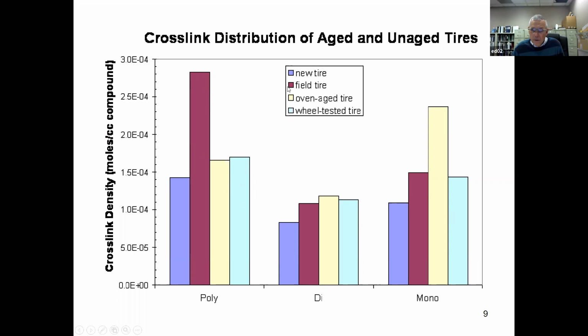So even though the field tire and the oven aged tire have the same crosslink density, all the crosslinks have to show up somewhere in here. But if you notice, most of the crosslinks that are formed in the field tire are found to be, quote-unquote, polysulfidic type, and most of the crosslinks that are formed in the oven aged tire are monosulfidic type. So they have the same crosslink density, but very different distribution of crosslink types.